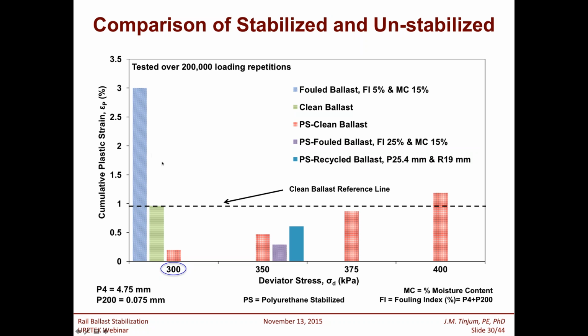So on the far left, the blue colored line is fouled ballast with a moisture content of 15%. The following is only 5%, so it's not huge. The clean ballast in the green, the middle line, is for your reference. And then finally, the polyurethane stabilized clean ballast, as you see the scale of how much plastic strain accumulation occurs over 200,000 cycles.